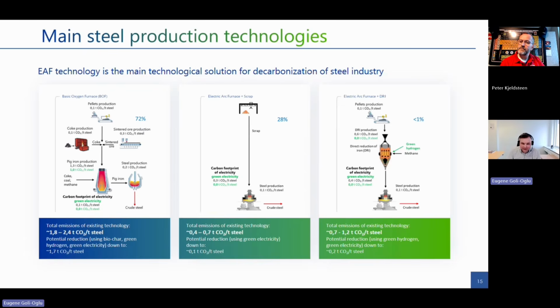if everybody decides to make material from scrap using electric arc furnaces, there will not be enough scrap. Because scrap is good, it's recycled steel, but it's still a limited resource. You still need to dig something from the ground, and then potentially a DRI solution could help with this. So in my opinion, for the next 10 years, the balance will change between BOF and EAF, but all of these options will still be relevant because in the end it will be some balance, but globally CO2 emission will decrease.